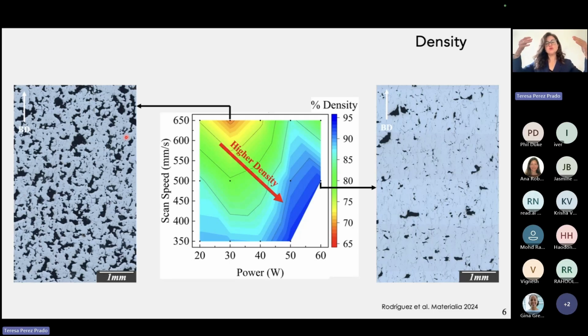And here I'm showing you two cross sections. These are two optical micrographs parallel to the build direction, which is the vertical here. This is the lowest. The material with the lowest density and the material with the highest density. And it is bad news that we are still, even in the conditions where we get the highest density, we still have quite a lot of cracks. So this is still there.